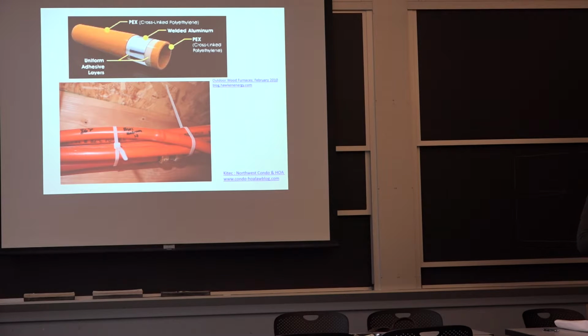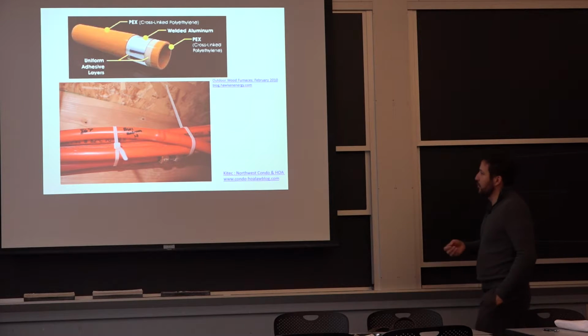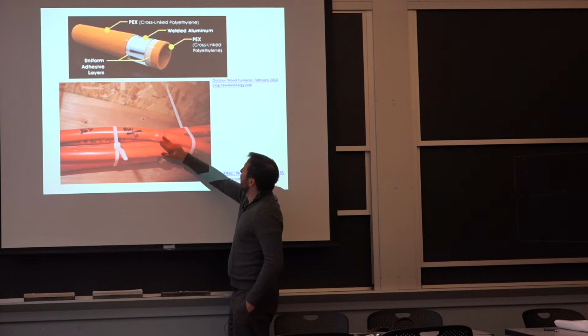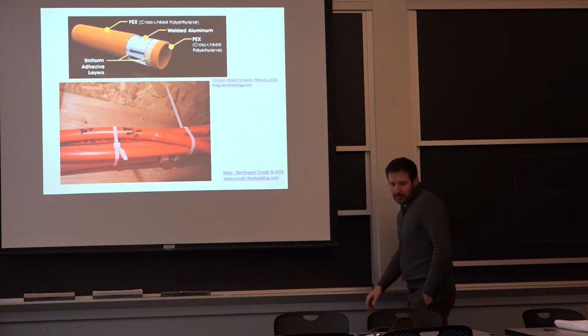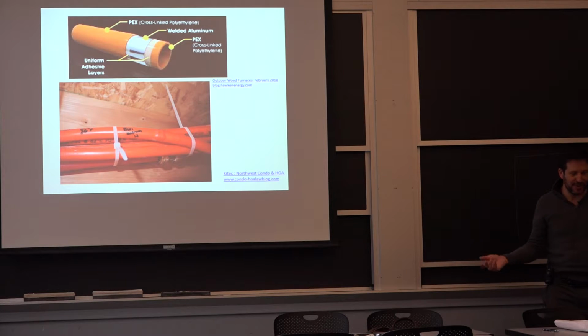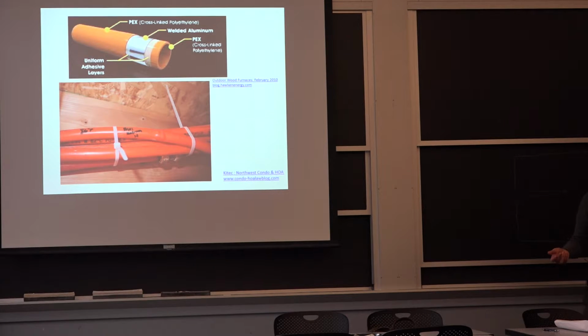So there was a drive to start using it for potable water, but the polyethylene itself wasn't built with enough antioxidant to resist the oxygen of the potable water. So they had a lot of blistering like you see here, and as part of their failure analysis, you see the blister on the outside and you start thinking, well, okay, what's going on? You find out that the aluminum corroded, and that's not really to be expected.